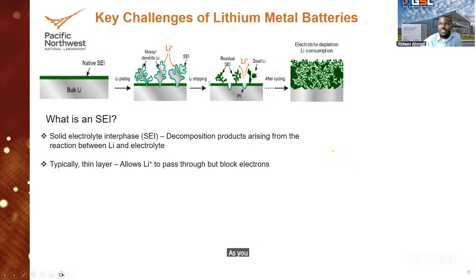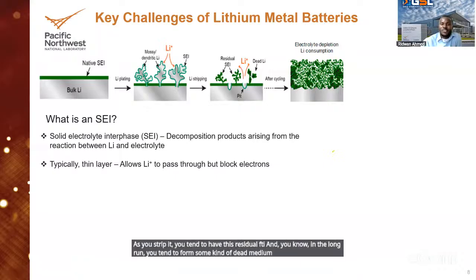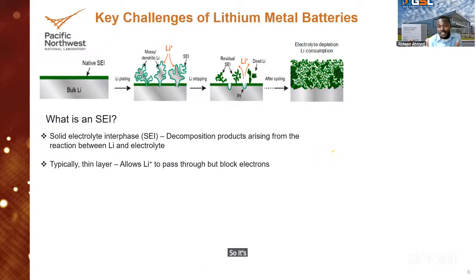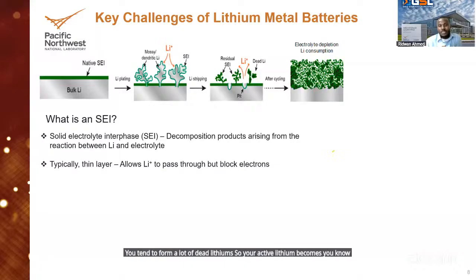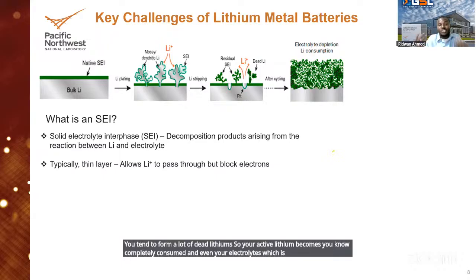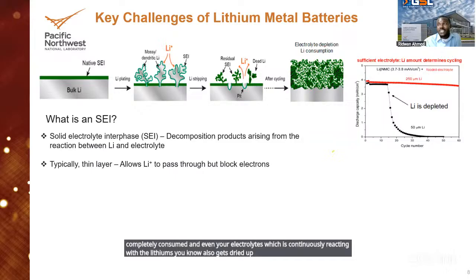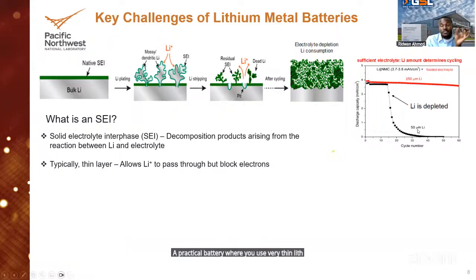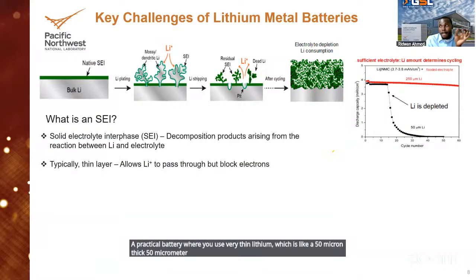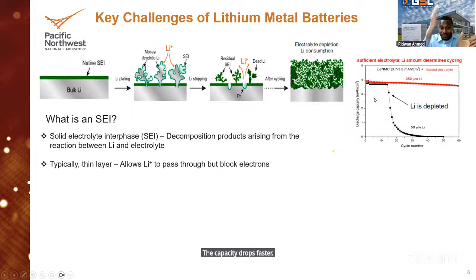As you strip it, you tend to have this residual SEI, and in the long run, you tend to form some kind of dead lithium, which doesn't have any contact with the bare lithium. So it's inactive. It doesn't participate in the chemical reactions any longer. When you cycle your battery for a long time, you tend to form a lot of dead lithium. So your active lithium becomes completely consumed, and even your electrolyte, which is continuously reacting with the lithium, also gets dried up. And the result is this: when you're using a practical battery with very thin lithium, like 50 micrometer thick lithium, the capacity drops faster. In other words, the cell fails within a short time.